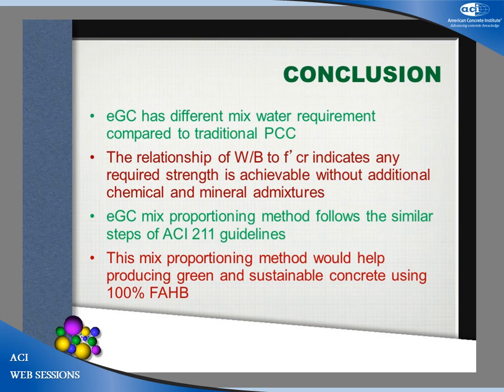Now let's come to the conclusion. Green concrete has a different water requirement per unit volume of concrete compared to Portland cement concrete. And we gave here the statistical model and the user-friendly chart. The second thing, we also developed the water binder ratio versus the f'cr chart so that we can get the water binder ratio. And more importantly, this green cement follows similar steps like the ACI 211. There is nothing much complicated.